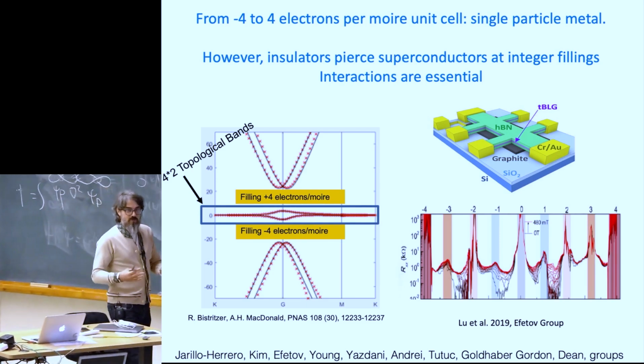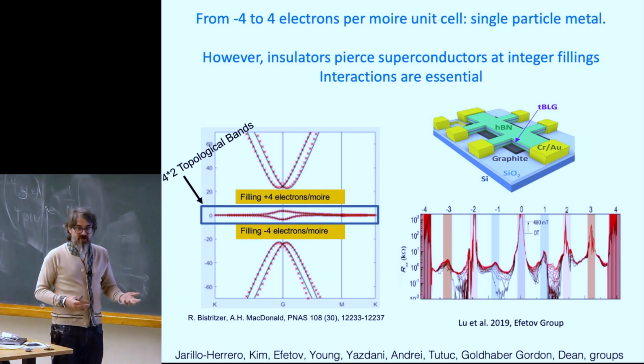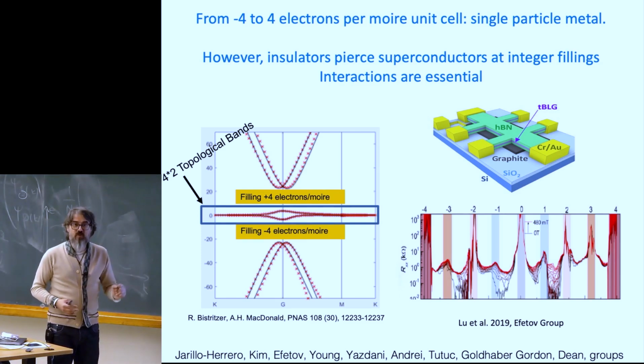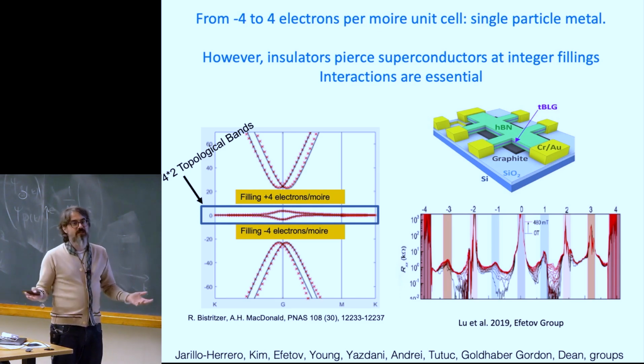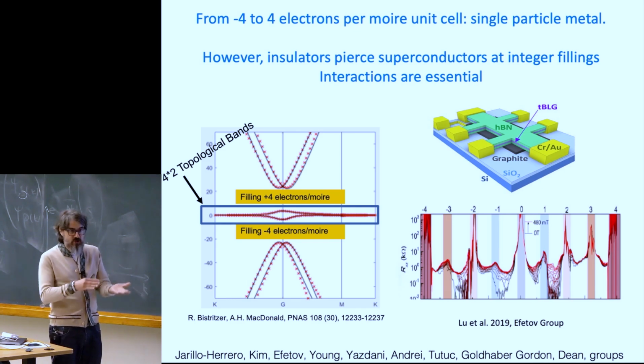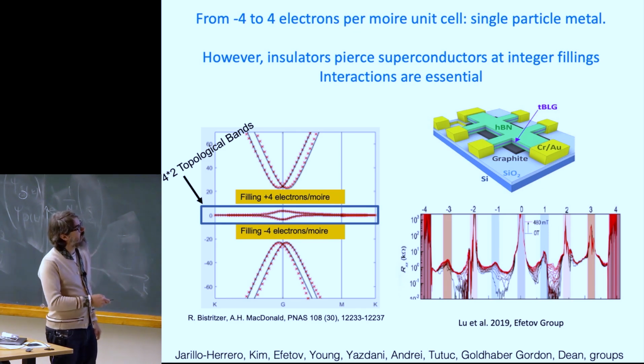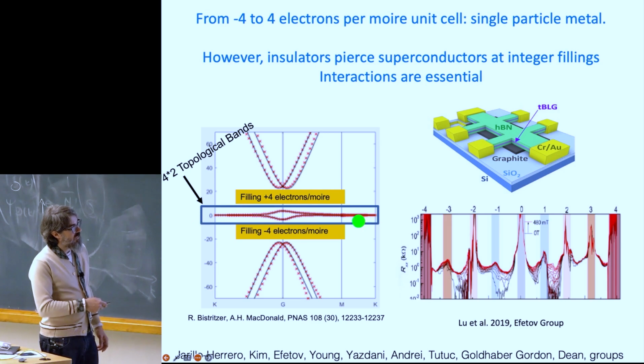Normally, you cannot dope a material with 1 electron per unit cell, or 2 electrons per unit cell, or even 0.5, 1 electron per 2 unit cells. There's just too much charge. If you dope it by an electric field, you need a huge electric field that first of all, you break down the material to dope that, to change the chemical potential, if you do it at the angstrom scale. So people in material chemistry, they use chemical doping, but that changes the properties of the material. So really what you want to do, just like in the quantum Hall effect, to keep the system clean, is you want to change its doping by an electric field, or its Fermi level by an electric field, and then the moral of the story is that you're stuck with small changes of electron number.